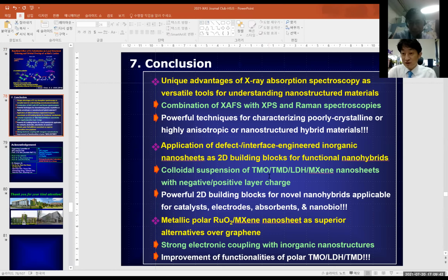We also use the LBL technique, layer-by-layer deposition. By using that, we can tune the stacking pattern with several nanosheets. We can actually do ABC, ABC, something like that, but only for film, not for the composite.